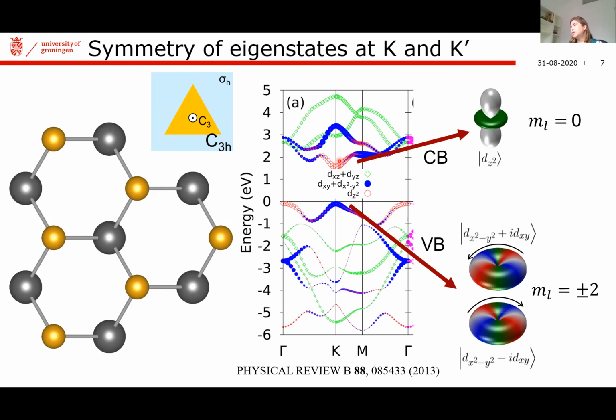Also, we know from tight binding calculations and from DFT that around the k and k prime points, where all of the low energy physics happens, the wave functions are mainly composed of d orbitals of the transition metal atoms. For the conduction band, these wave functions are formed by dz square orbitals. These are orbitals that don't have any orbital angular momentum, and that is emphasized by the fact that if you think of the color with which I plot these orbitals here as the azimuthal phase, so the phase winding in the plane, you can see that this phase is constant for the dz square orbitals.